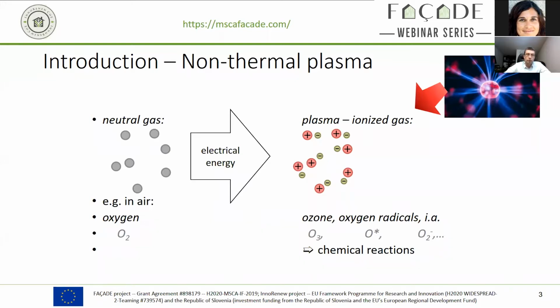What you do get from the plasma, however, are different reactive species. So, for example, if you have a gas where oxygen is present, you get a lot of different reactive oxygen species, including ozone, oxygen radicals, hydroxyl ions, typically also other ions, and all these different species can then foster chemical reactions that you can utilize for the different modifications of, in this case, surfaces.